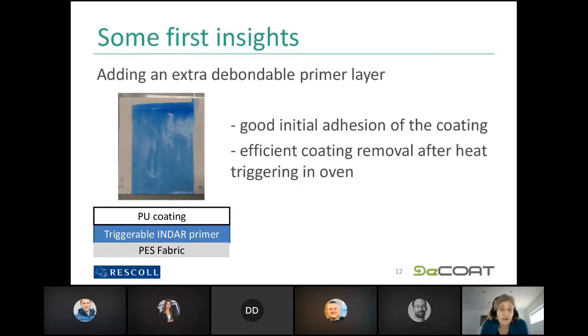In this case, we already saw a good initial adhesion of the coating, because this is also very important, because during the use phase, it still has to meet the functional requirements. And we could also see upon heat triggering in the oven that we had an efficient removal of the coating.